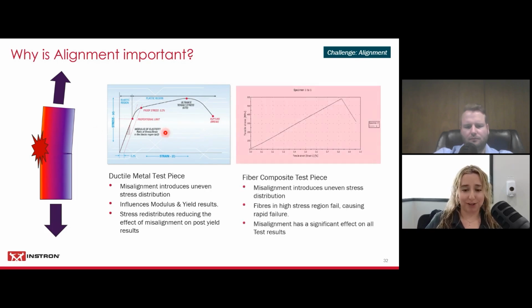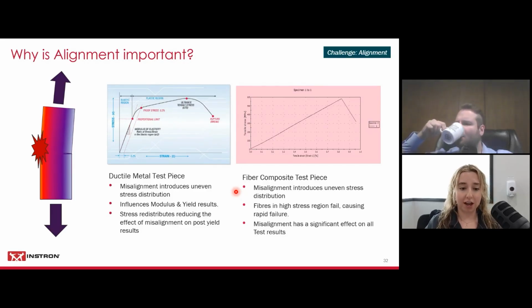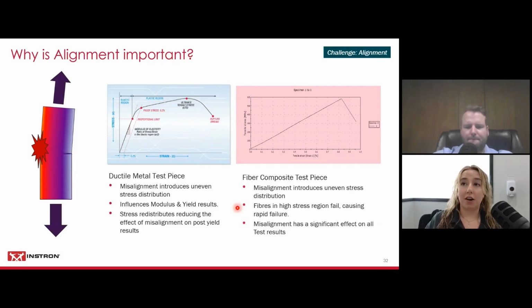If we have a composite that is misaligned, composites are very sensitive because they're typically brittle, they're typically low strain, and if you have fibers aligned in a certain orientation and you've already pre-strained those fibers, it's very likely that you've actually damaged the specimen when loading before we've even started the test. So we've created uneven stress strain distribution. We have some fibers that have started to fail in one region, and we're going to rapidly fail shortly thereafter. So we're going to have effects not only on our modulus and yield, we're actually going to see effects in our tensile strength and our ultimate tensile strain, so we're going to see worse results within our composites if we are misaligned.